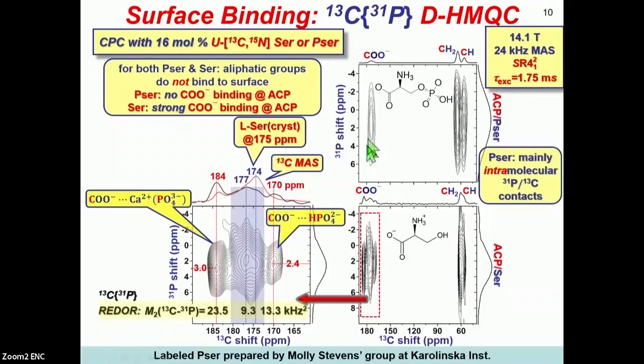Here you see the resulting HMQC spectra. And I would like to comment here that under our experimental conditions, the signals that are detected are from groups that are in close proximity to the inorganic phosphates, but that also includes not only the carbon sites in functional groups directly bonded, but also other groups a little bit further away. This is, for instance, obvious here where we see correlations between the aliphatic carbons for serine,